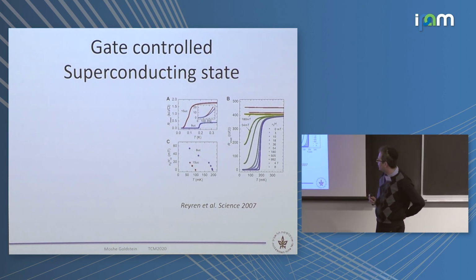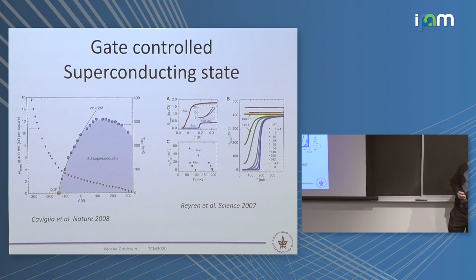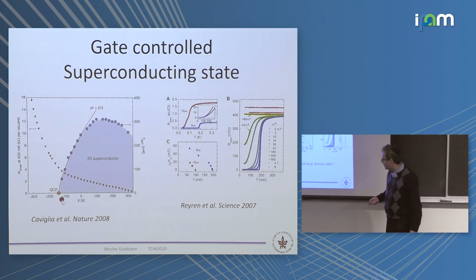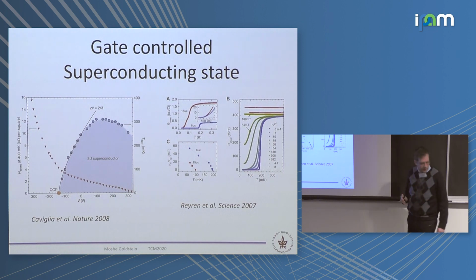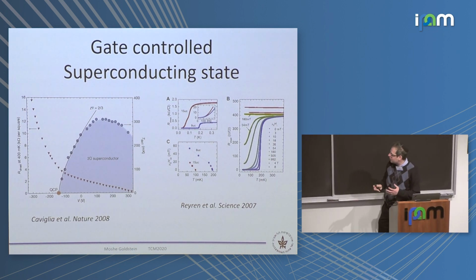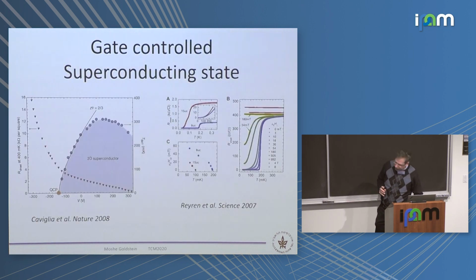Okay, so I told you that the interface is, what is important? So the interface is becoming conducting, it also actually becomes superconducting. And not only it becomes superconducting, but as function of gate, you can have a negative gate, which basically depletes the system. And then the TC goes to 0, although actually it goes to 0 while you still see some conductivity. So you don't need to fully deplete to see 0 TC. And then it increases, which is OK, and then it decreases. So we have a dome, and this is unusual. It's very far away from, you know, some integer filling or something like that would be like here at inaccessible regime. We are only filling the bottom of the bands. So something like that is unusual, and people started immediately thinking about relation to high TC and other more fancy stuff. Okay, so this needs to be understood.